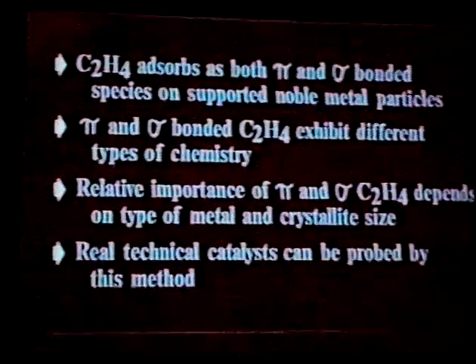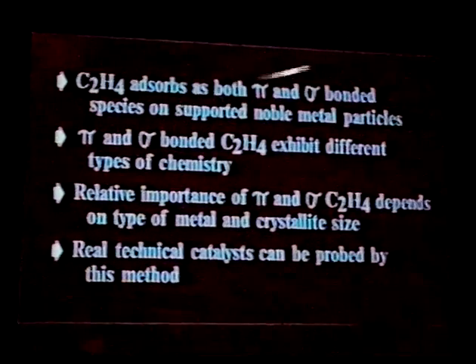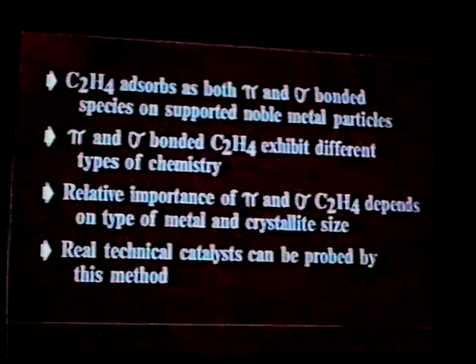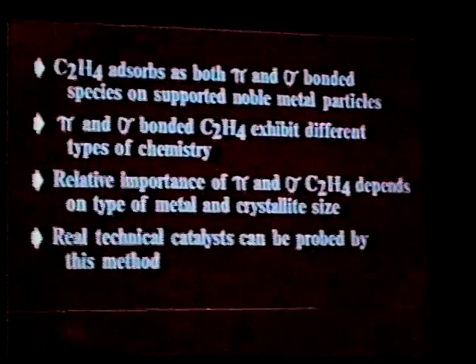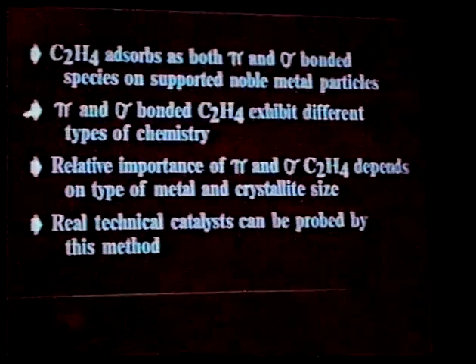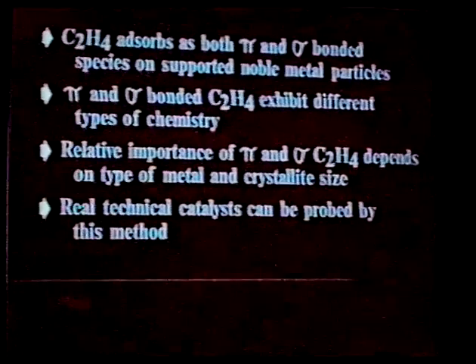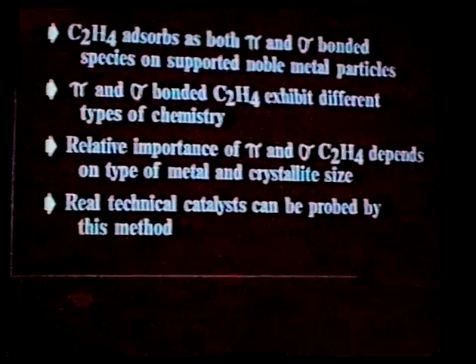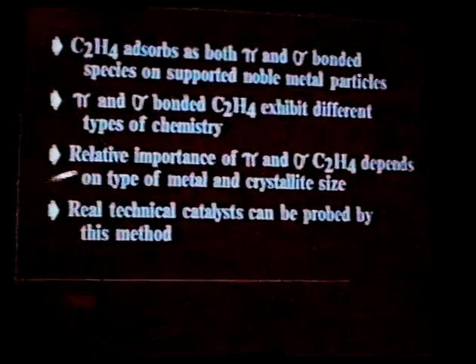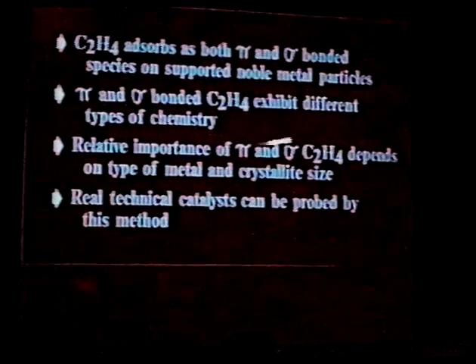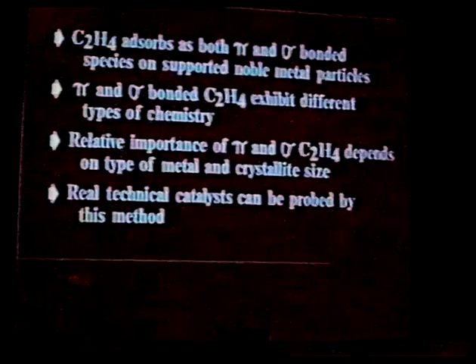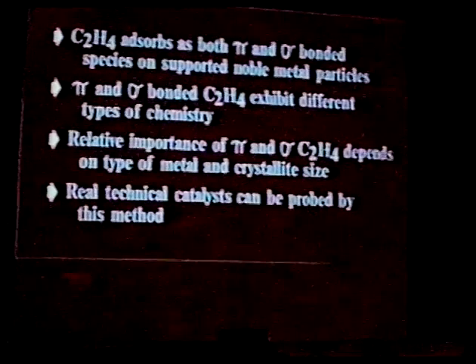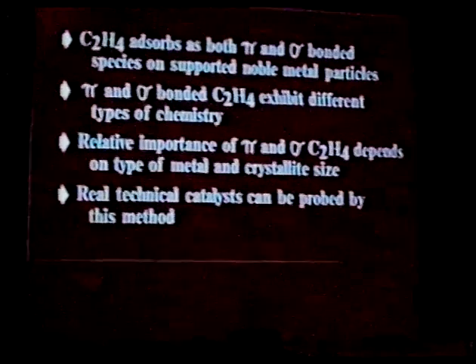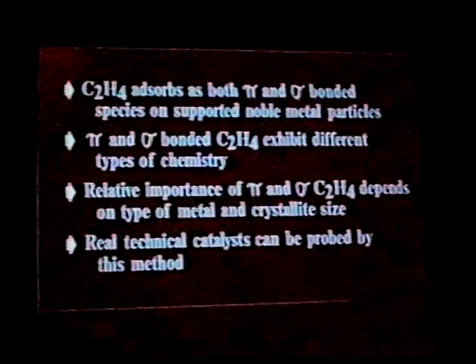Well, what I'd like to do is show you that ethylene adsorbs in two different forms at low temperatures on noble metal clusters, and that they exhibit different types of chemistry from one another, and that's relatively independent. Also, I'd like to show that the relative importance of the pi-bonded or the di-sigma bonded type of ethylene depends on both the type of metal and the crystallite size of the particular metal that you're using.